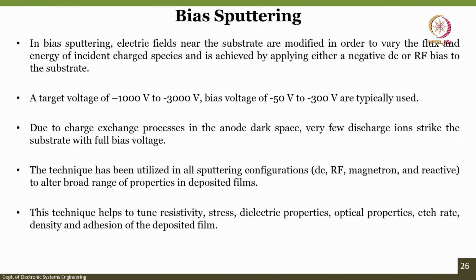By changing this bias voltage, you can have the properties of the film changed, and again when we go for material characterization, in material science, right, you need to change the properties of the film, and that could be changed by the effect of the bias. The technique further helps to tune resistivity, stress, dielectric properties, optical properties, etch rate, density, and adhesion of the deposited film. So, not only the deposition, but also how to change the properties of the material, right, whether it is a dielectric property or an optical property, or whether it is improving the etch rate or increasing the resistivity, all this can be tuned with the help of these parameters, right. So, that is the advantage of bias sputtering.